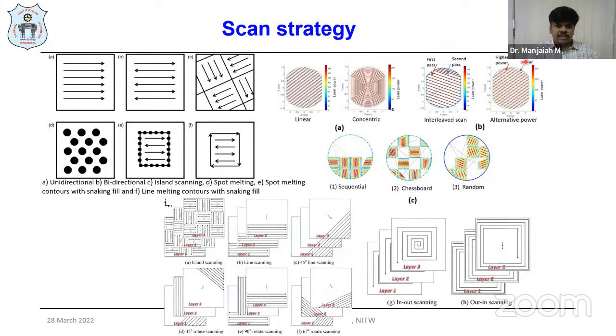The other barriers are the scan strategies. There are n number of scan strategies we are using in the manufacturing process, depending on what kind of component we fabricate, whether it is simple, cubic, rectangular, cylindrical, or maybe hollow structures. We have to follow different scan patterns: unidirectional, bidirectional, island scanning, spot melting, as well as different filling patterns like chessboard, sequential, random, concentric, linear, zigzag, 45 degree orientation. We can even define our own scanning strategies, maybe in and out, out and in. These kinds of strategies will directly affect the quality of the components which are fabricated.